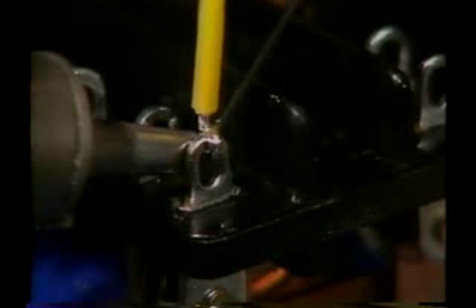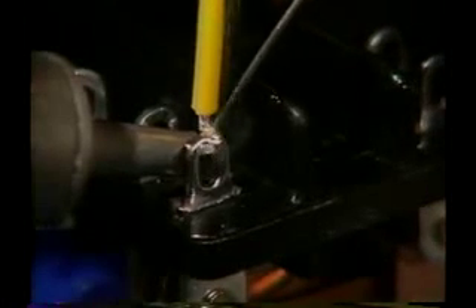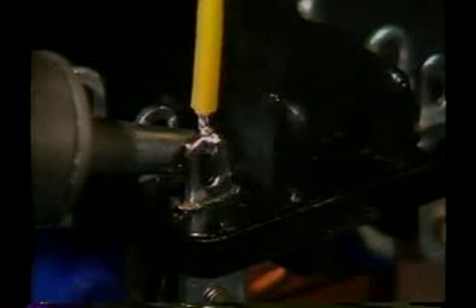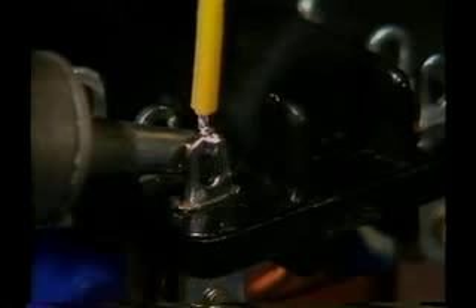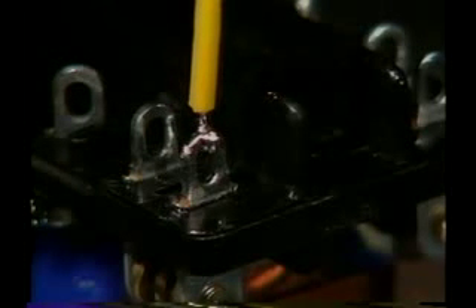Additional solder is then applied on the opposite side of the point of contact to form the necessary solder fillet. The solder wire is removed when a sufficient amount of solder has been added to the joint. Finally, the iron is withdrawn at the same angle it was introduced to the joint.